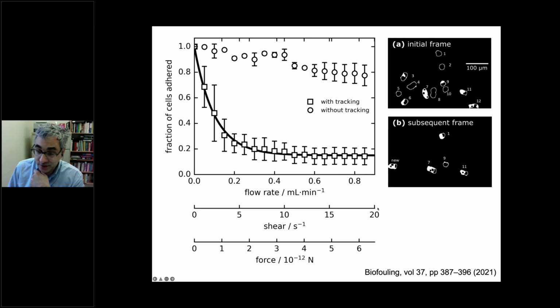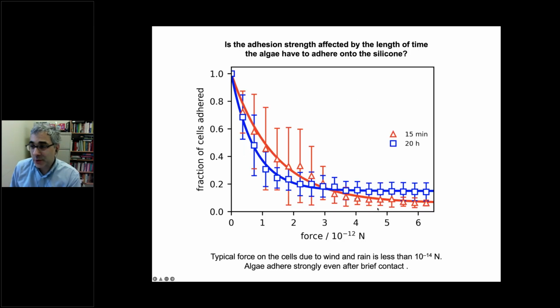different environmental conditions. So the first thing I'll show you is once we had the setup, we were very curious to see what difference would it make if we had the algae adhering onto the surface for 15 minutes before we subjected them to this washout stress versus if we gave them nearly a day or 20 hours to adhere on the surface. And the hypothesis is that if they get a chance to interact with the surface longer under quiet conditions, they may be adhering more strongly. And we observe just the opposite.